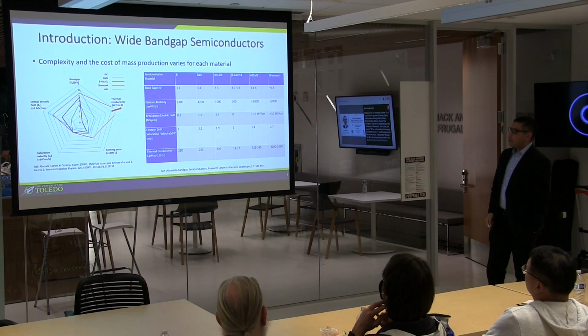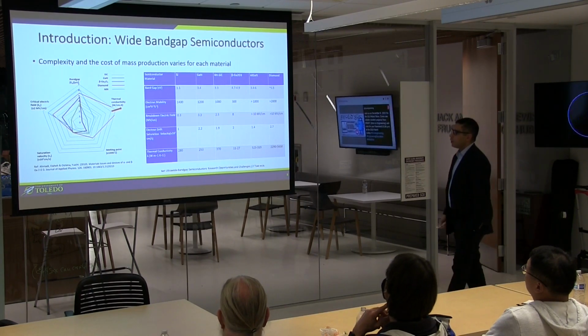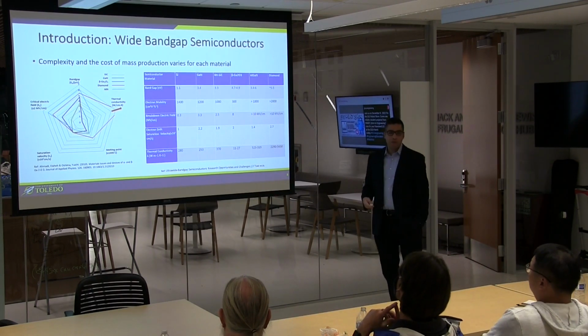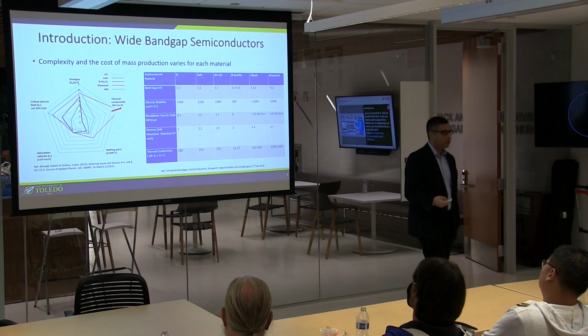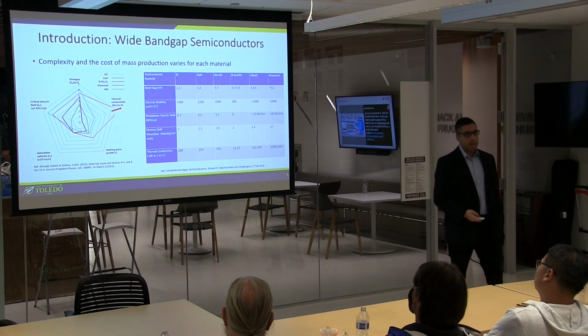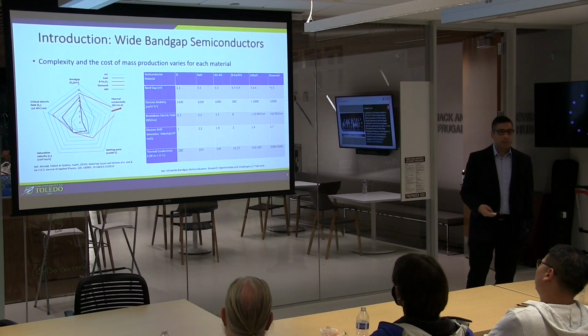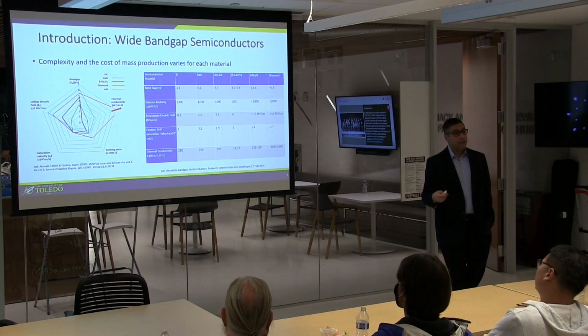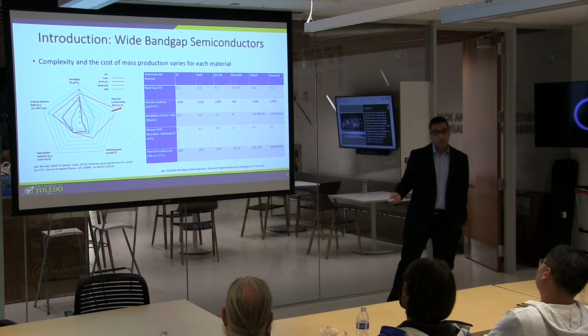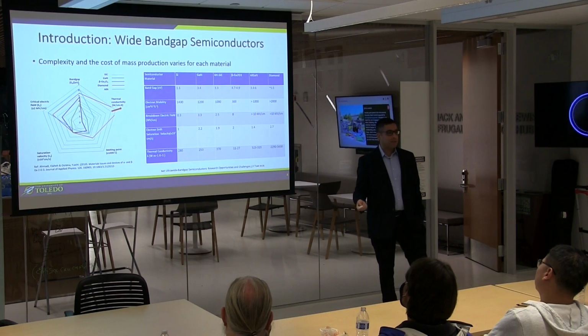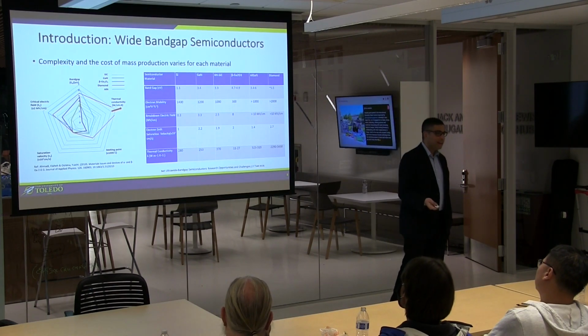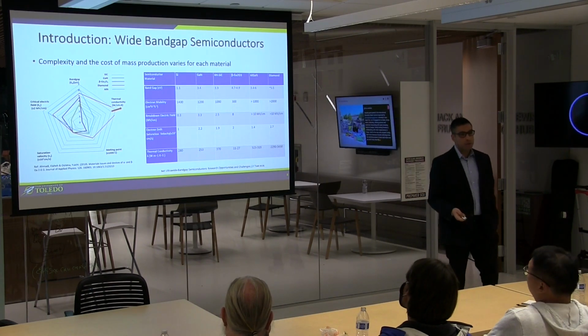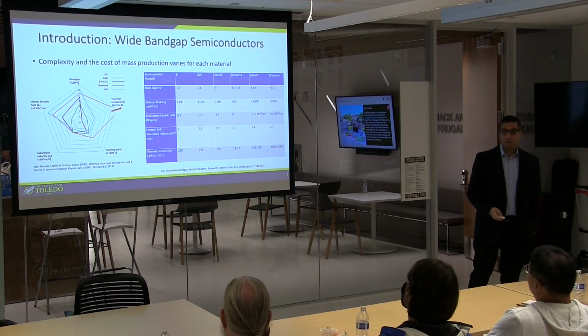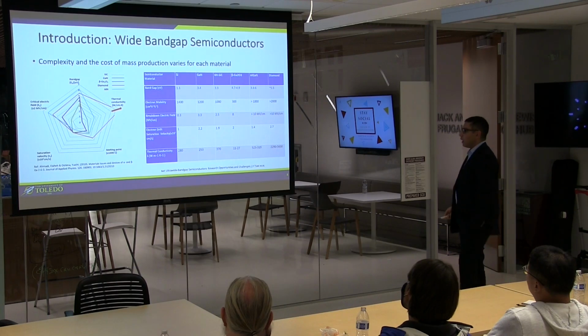Every material has its own benefit. As I mentioned before, silicon carbide is really great for thermal conductivity, really good for high temperature operation capabilities. GaN's got the higher electron mobility. GaN, theoretically speaking, can go up to 20 kV. Silicon carbide, we think, starts to run out of steam at 15 kV. And then, of course, the ultra-wide bandgap materials go higher than 20 kV, theoretically speaking. That's why we need the research.